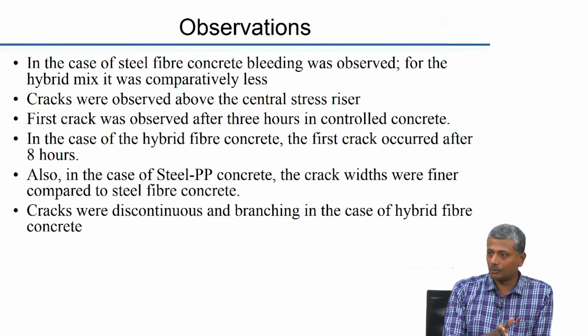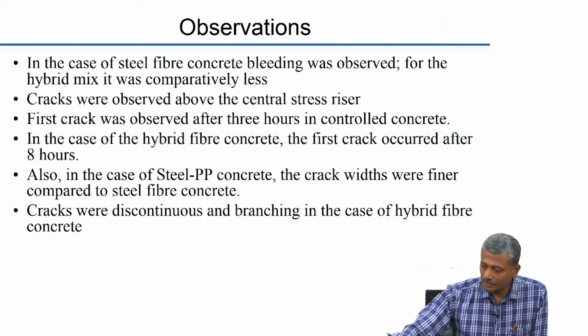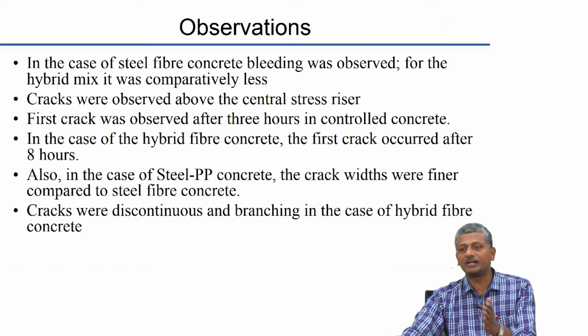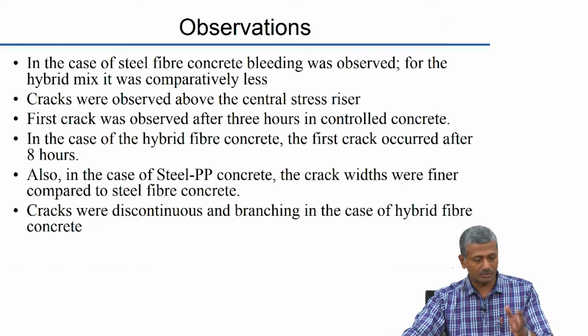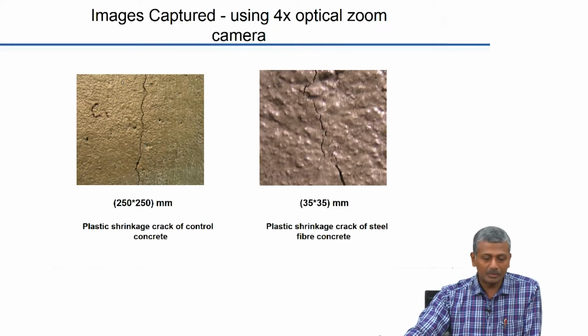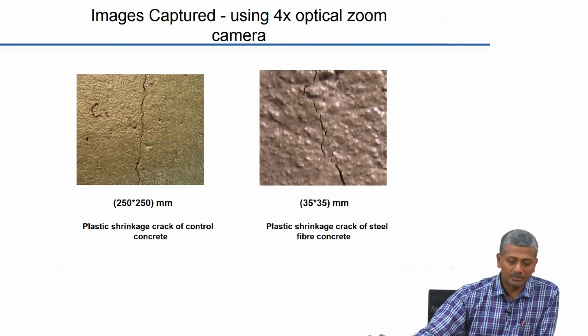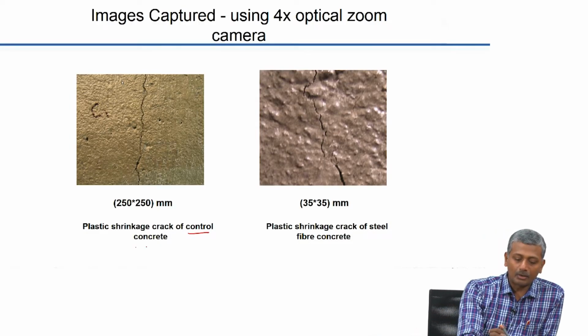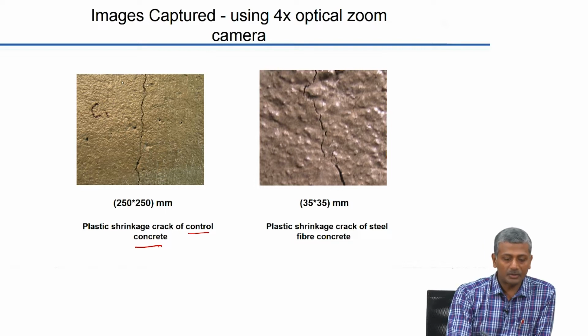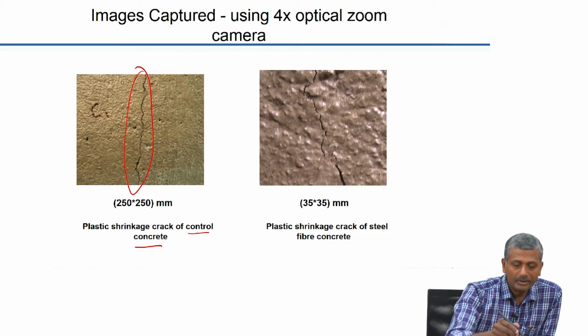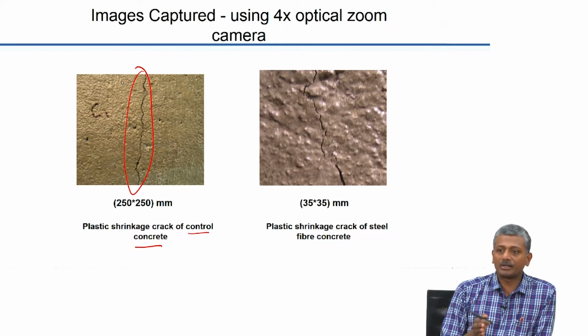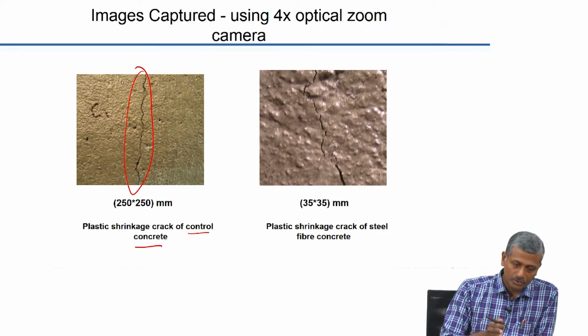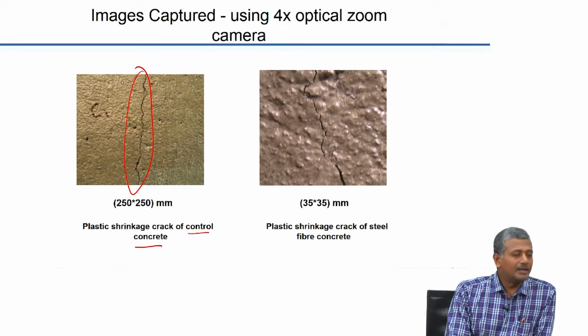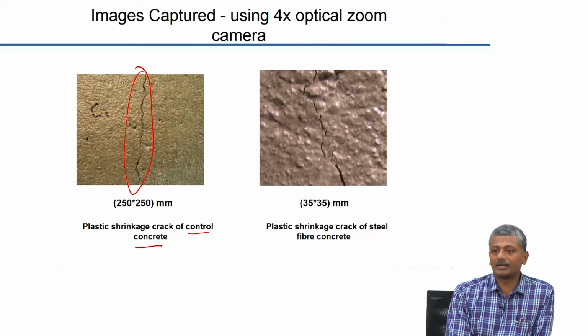So again, now in terms of the observations, obviously because of the stress riser, the crack appeared right exactly over the stress riser, and the appearance of the crack happened at different times for the different types of concrete. So instead of the words, I will show you the actual images which correspond to the appearance of the crack. So this is the control concrete without any fibers, and you see that this crack is almost straight. It occurs right over the stress riser, and it is almost straight running across the entire length, and the width is almost constant across the entire length.